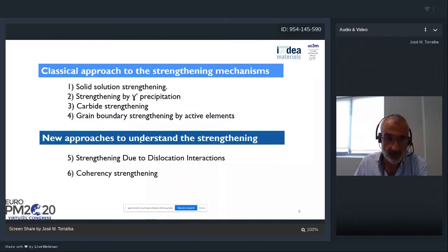So the classical approach to the strengthening mechanisms in superalloys are these first four things. First, the solid solution strengthening. We can strengthen by gamma prime precipitation, as we did in nickel and in these new cobalt alloys. The carbide strengthening and the grain boundary strengthening by some elements like boron or even carbon in the border of the grains. But we have to analyze new approaches to understand this good strengthening in superalloys. One is the strengthening due to the dislocation interactions, and the last one is the so-called coherency strengthening.